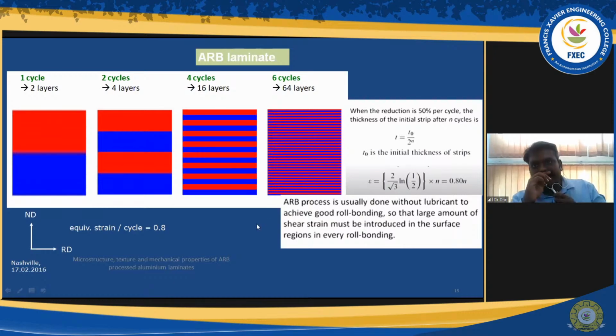The limitation in this method is that for better bonding you have to do the rolling without lubrication. Usually we do conventional rolling with lubrication, but in this case you should do it without lubrication, because otherwise it won't give good bonding. When you are rolling without lubrication, that may induce shear over your sample surface, which sometimes leads to a detriment to your property. So that is the limitation.